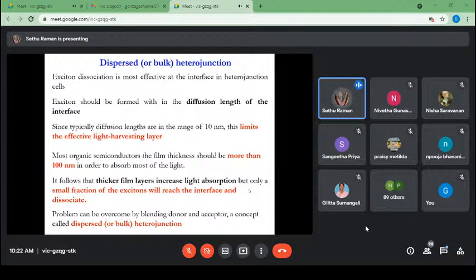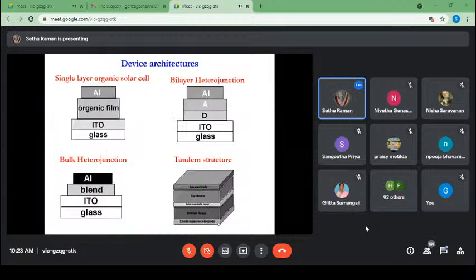So we face a dissociation problem in the thick layers fabricated in solar cells. If you prepare a thick layer of more than 100 nanometer, it will definitely absorb a lot of light, but dissociation is very difficult. Diffusion is a big problem in that type of layer. That problem can be overcome by blending a donor and acceptor. Suppose you are using a traditional heterojunction; I told you about this layer.